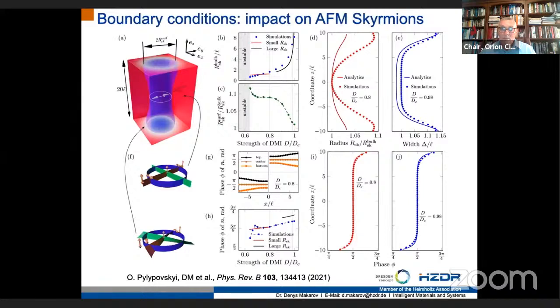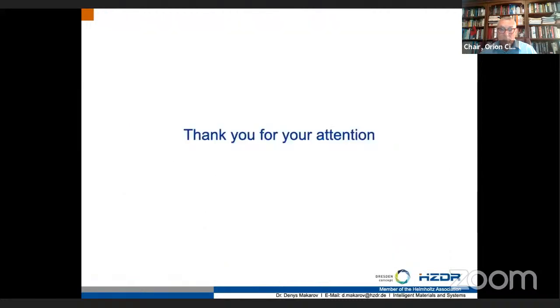on each side. Therefore, if we want to work with the bulk-like properties of a skyrmion or the domain wall, we have to make sure that the sample thickness and the sample width are sufficiently large, being at least in a range of 15 to 20 exchange lengths to enable the bulk properties of these textures. This is of course important for the design of antiferromagnetic racetracks, which are based on antiferromagnetic domain walls and antiferromagnetic skyrmions as information carriers. At this point, I'm at the very end of my talk.